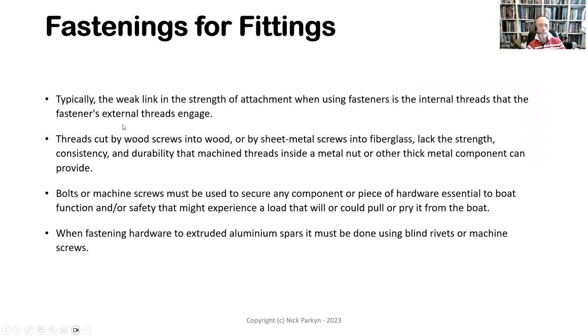Fastening fittings is very important. Typically the weak link is the strength of the attachment and the internal fastener threads that are engaged. And so when we find that you're using threads cut by wood screws into wood or by sheet metal screws into fiberglass or into aluminium masts, they really lack the strength and consistent durability that machined threads inside a metal nut or other thick metal component can provide. So again, I think when we do these inspections, we need to start also looking at whether the appropriate type of fastener has been used. Bolts or machine screws must be used to secure components which are essential to the boat function and could pull or pry loose from the boat.